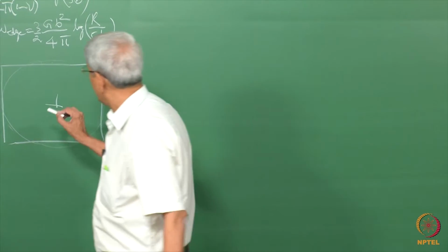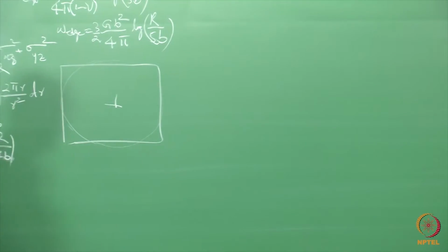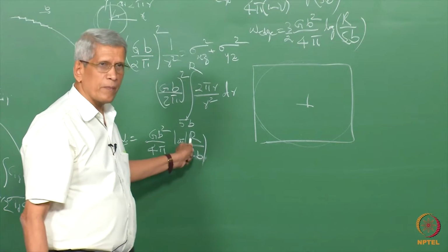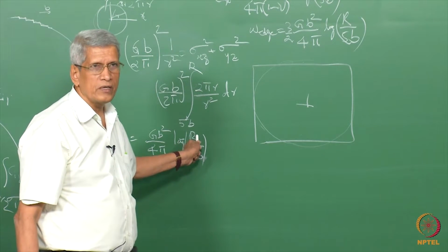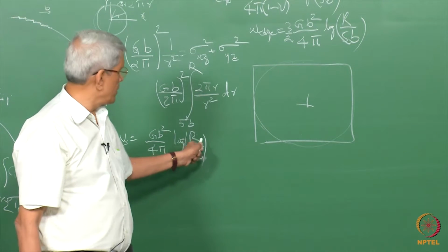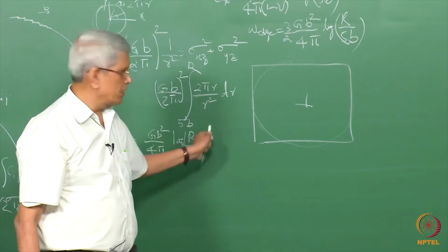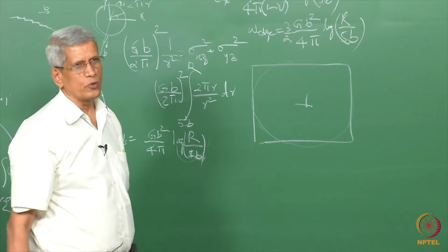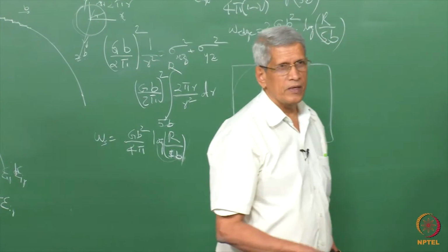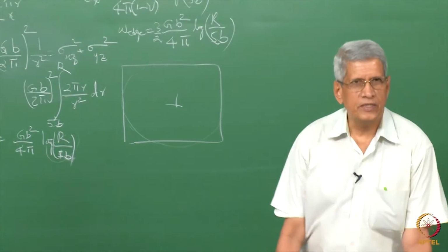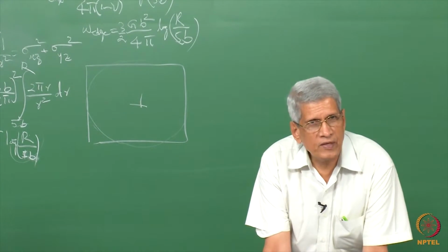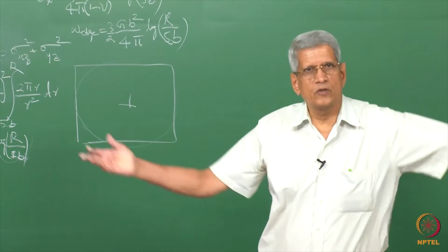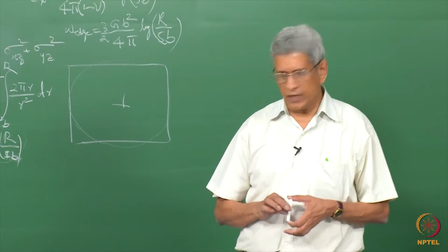Since this term which corresponds to the distance comes in a log scale, if it changes from r equals 1 to 100 or r equals 10 to 100, this value can turn out to be from 1 to possibly 2 maximum, correct? So on a log scale only the increase is going to take place. Because of that, we find that changes are not much even as large volumes are being taken. Okay, that's one.